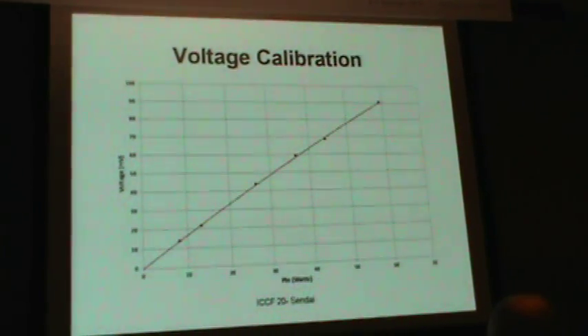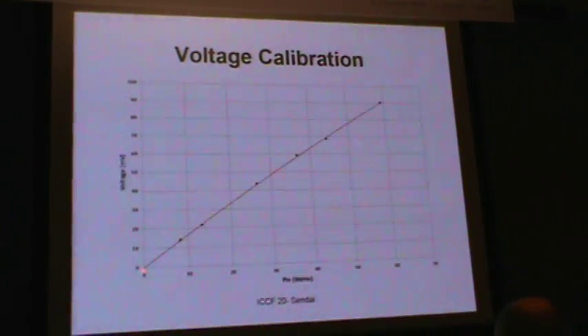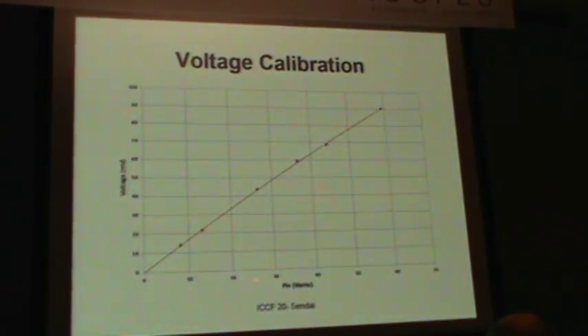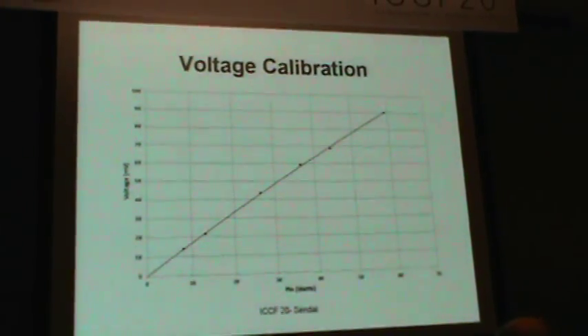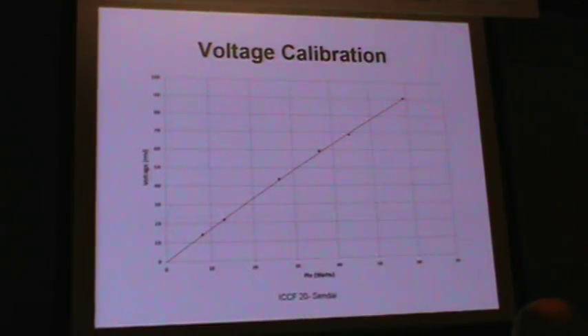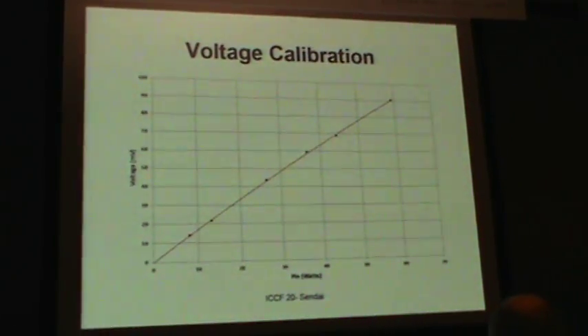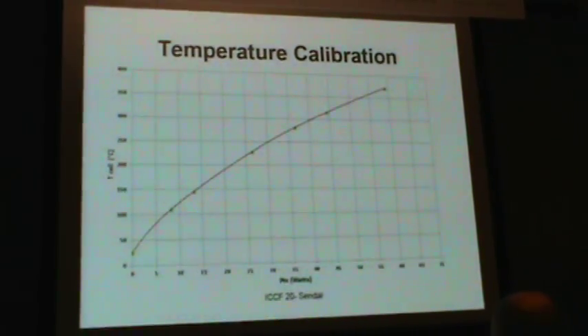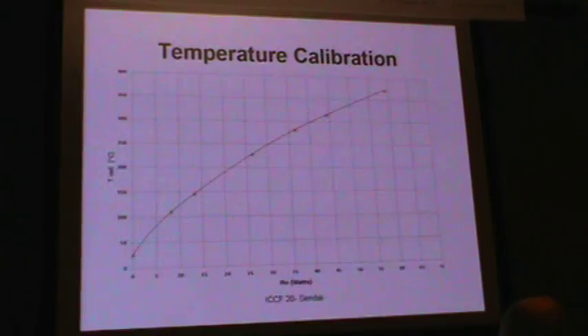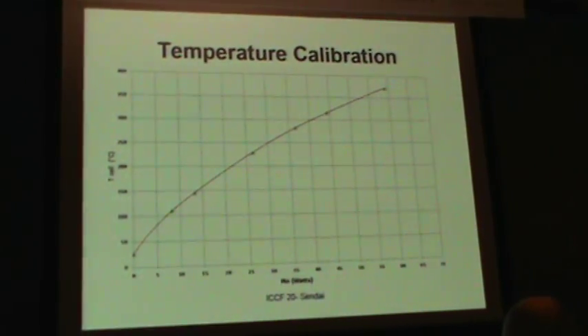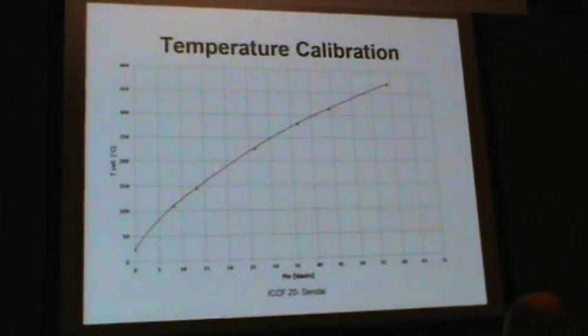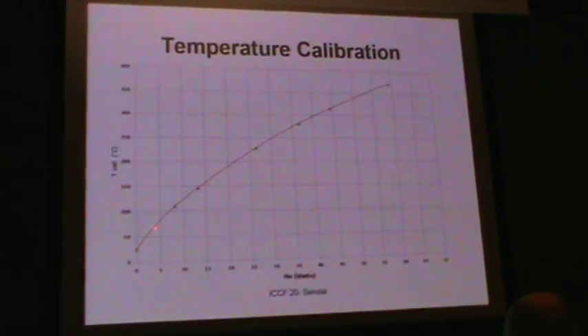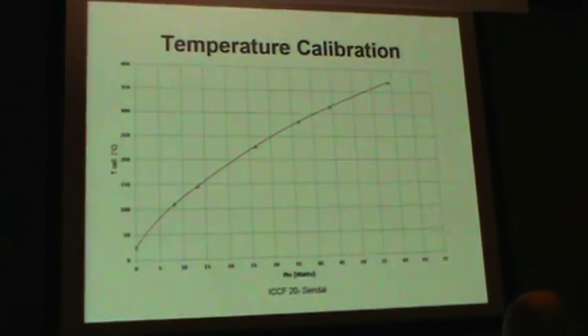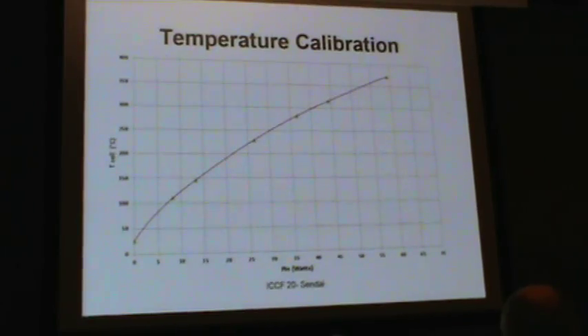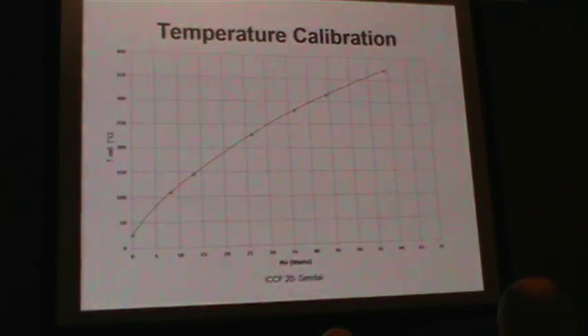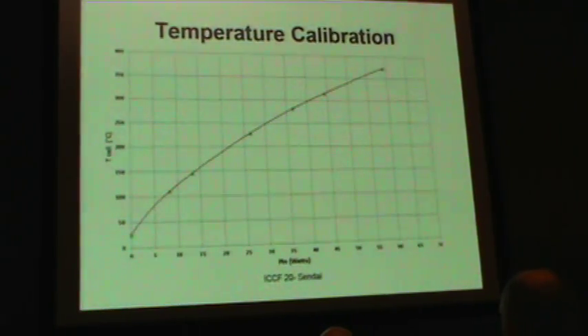So I have to calibrate the system first. When I put the heater alone, I have the voltage, in millivolts, versus the power input, and it's pretty much a smooth curve. It's not linear because there are losses in my design, but it's calibration. I've calibrated both the voltage and also the thermocouple that's inside, so I can use the two indications. To make sure you don't make any mistakes, you need at least two pieces of information. It's not because you find a Roman coin in the floor that the Romans came here. Maybe someone dropped it. So you need two indications at minimum to make sure you're correct.